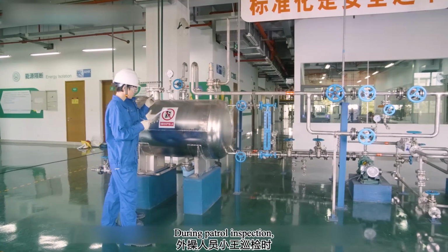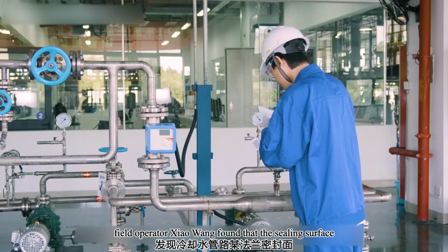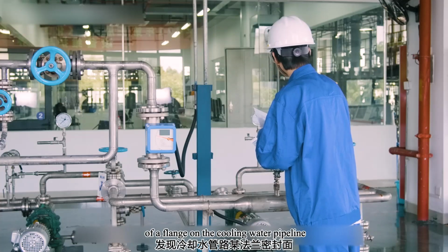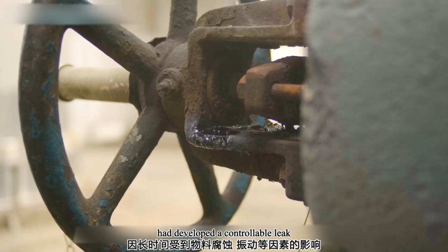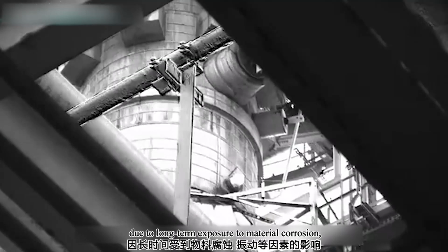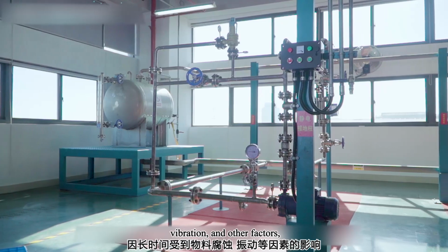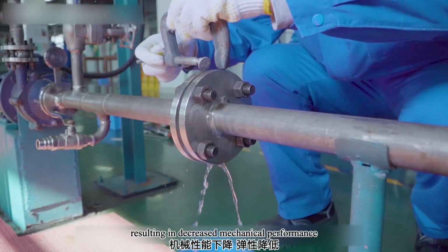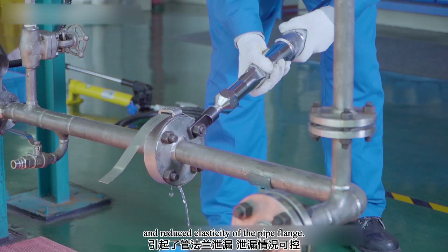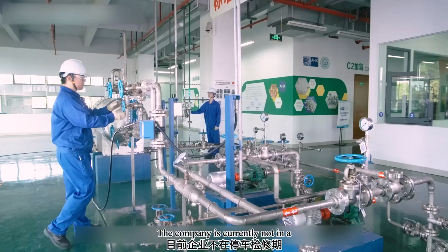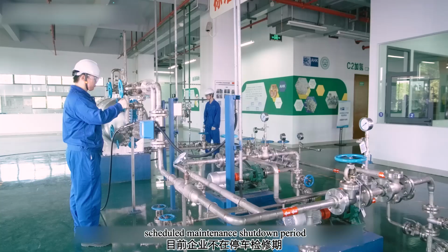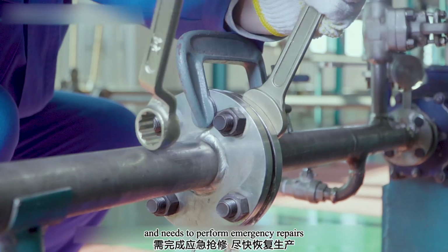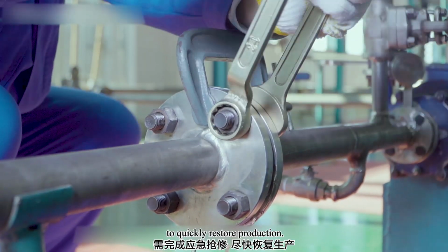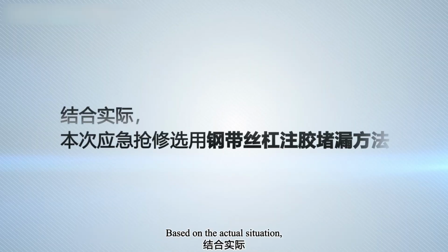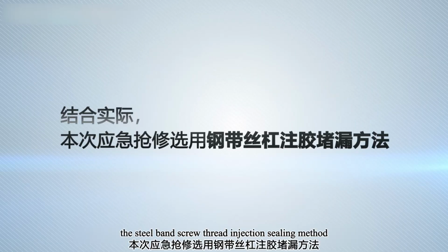During patrol inspection, field operator Xiao Wang found that the sealing surface of a flange on the cooling water pipeline had developed a controllable leak due to long-term exposure to material corrosion, vibration, and other factors, resulting in decreased mechanical performance and reduced elasticity of the pipe flange. The company is currently not in a scheduled maintenance shutdown period and needs to perform emergency repairs to quickly restore production. Based on the actual situation, the steel band screw thread injection sealing method was selected for this emergency repair operation.